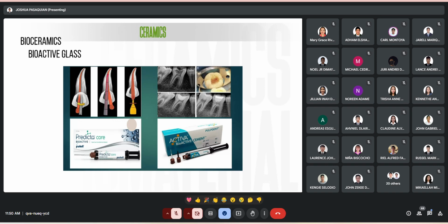because an in vitro study showed that the ions released by bioactive glass particles did not inhibit the growth of human dental pulp cells, but it showed that when bioactive glass was used for direct pulp capping, a dense dentine bridge was formed. Bioactive glass is also used in gutta-percha since it enhances its bonding to dentine walls without an adhesive. It also provides a tight seal, increases the pH, and provides antimicrobial action.